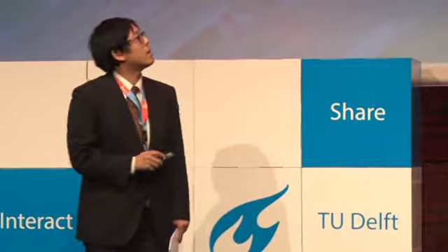This slide summarizes the test specimens. Test materials are class C wheel steels, 0.7% carbon, and the microstructure is pearlite steel, and the hardness is 330. Wheel test specimens were taken from the actual wheel rim, and roller test specimens were taken from the material billet for wheel.